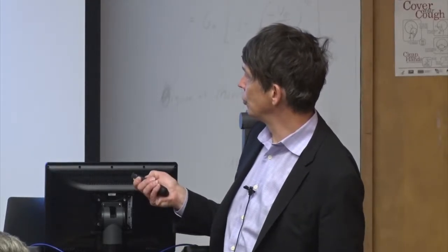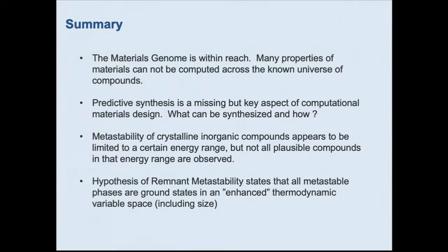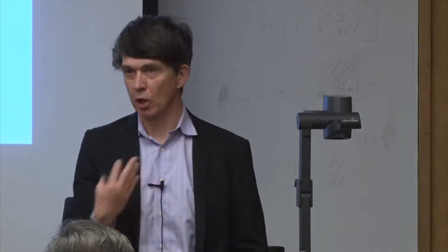I talked a bit about the issue of predictive synthesis. And one finding of ours is that metastability, and I stress the limitation here, of crystalline inorganic compounds seems to be limited to a fairly low energy range, but the corollary to that is not true, right? Not everything in that energy range seems to be synthesizable. And we are currently working with this hypothesis, and it truly is a hypothesis, not a theory, that most metastability is what we call remnant metastability, in the sense that it's only metastable because it was stable once in some enlarged thermodynamic space. It is not an accident of nature.